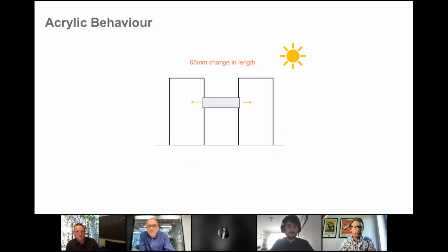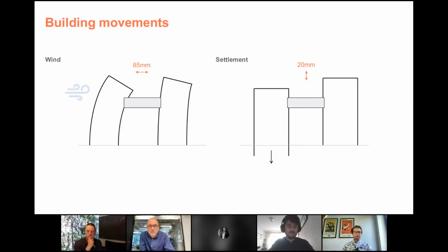Another thing is that on a sunny day, compared to a winter's day, a summer day, it will be 65 millimeters longer, and this movement has to be accommodated. It's not just the movement of the acrylic due to thermal expansion, but also the building movements that we need to accommodate. All buildings move when the wind blows to some extent. So we've got a differential movement of the two buildings of 85 millimeters. And then we've got potential settlement of one building versus the other, especially as one site was built a lot earlier than the other, and the other may potentially settle quicker.